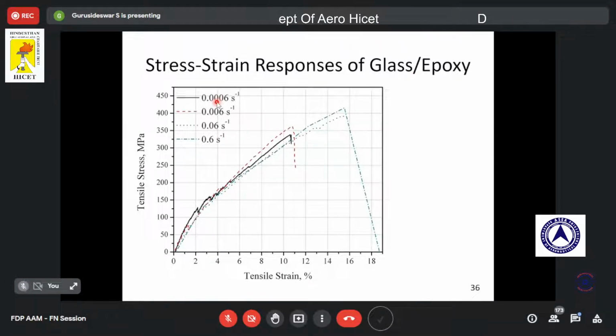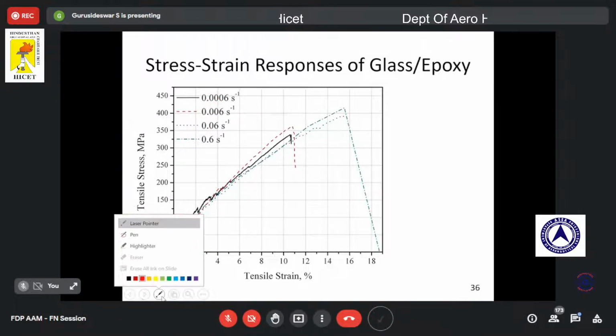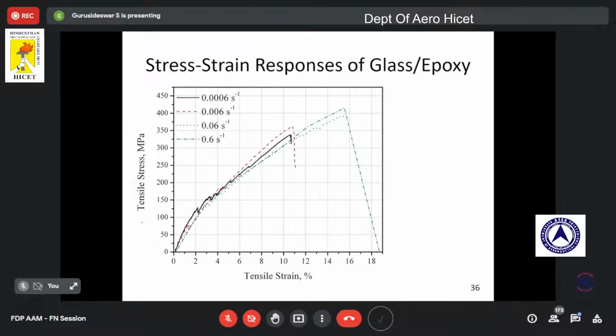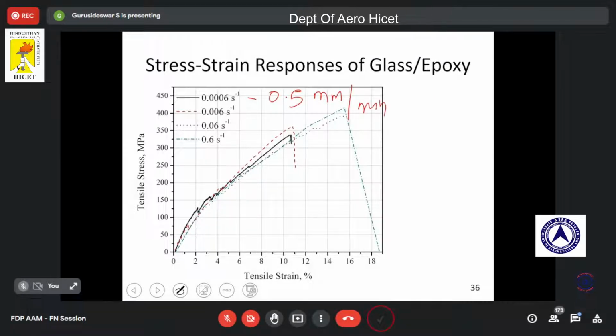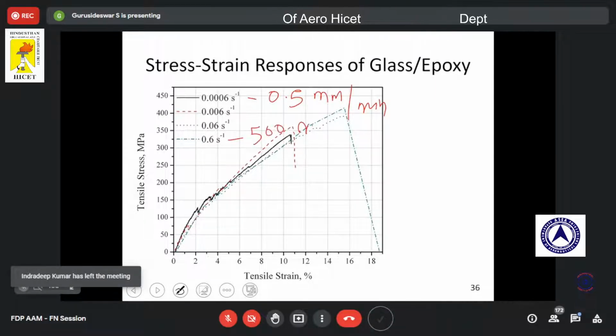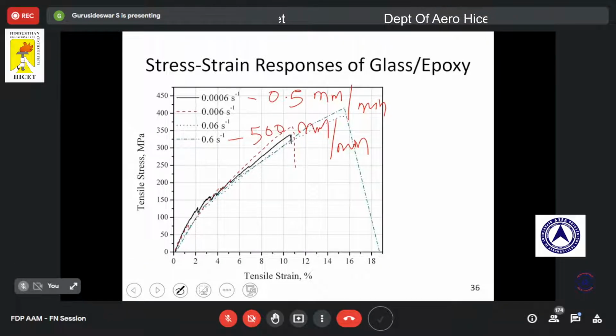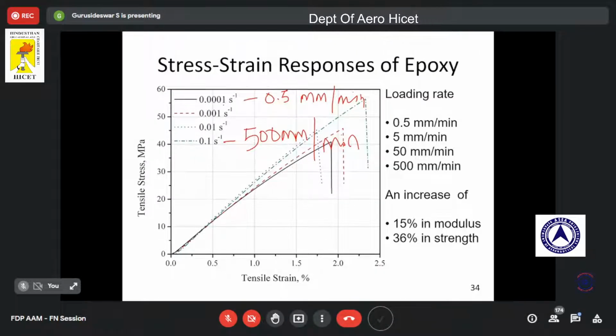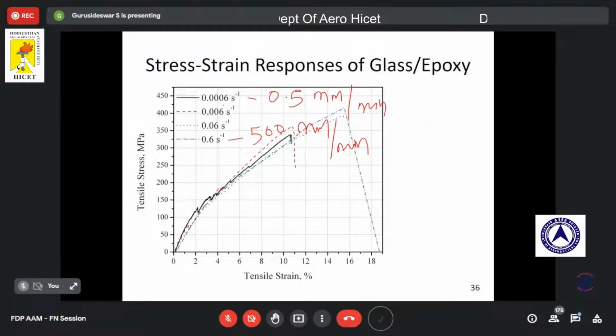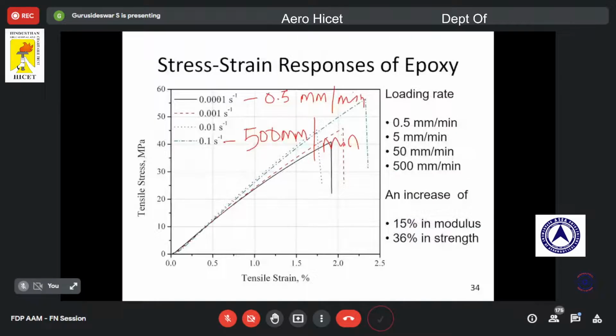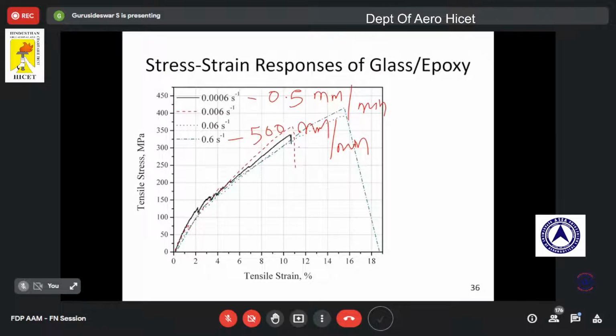Again, this 0.0006 corresponds to 0.5 mm per minute, and this corresponds to 500 mm per minute. And one can question me why the number is changing, because for epoxy samples I get 0.001, but for glass epoxy I'm getting 0.0006. The reason is that the gauge length of the sample is 50 mm, but here the gauge length is, I think, 25 mm. So that's why we have a change in this data.